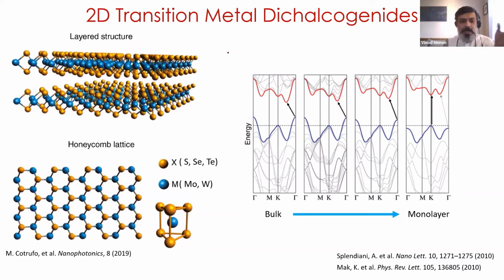Well, unlike graphene, which is just made of one sheet of carbon atoms, these materials are actually made of 3 layers of atoms, which makes one monolayer, with the molybdenum or the tungsten atom sitting in the middle, and the sulfur or the selenium or tellurium atom sitting one plane on top and one plane at the bottom. So these 3 atom layer thick layer makes one monolayer of the material, and between these layers, it's held together by a van der Waals force, so it's easy to remove them. Of course, following in the footsteps of graphene, the way people started working on these is also using the Scotch tape exfoliation technique. So you put a Scotch tape, you peel it off, and you get a few layers, and then finally a monolayer of this material.